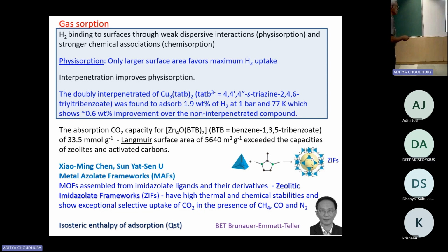And this particular MOF is zinc with BTB, benzene tribenzoate compound. It shows very high uptake of CO2. This compound shows high surface area. By the way, there are 2 different ways of measuring the surface area. One is Langmuir and the other one is BET. Of those, BET is more useful for MOFs. But although I'm saying all these things, many of them report both Langmuir as well as BET. He said it exceeded the capacities of zeolites and activated carbons. That's why I put it in. It is much better than what is available currently.